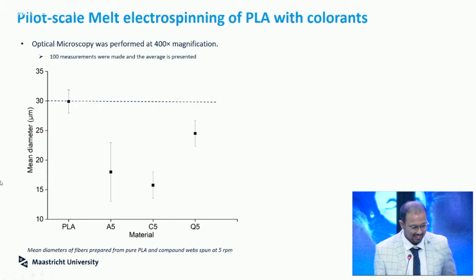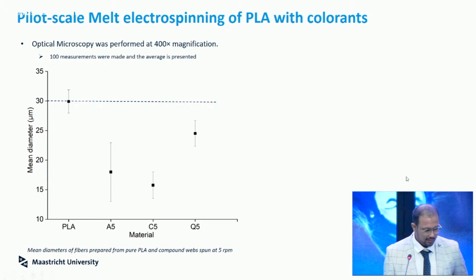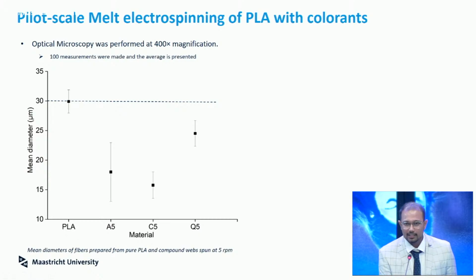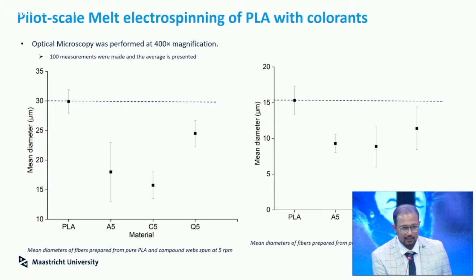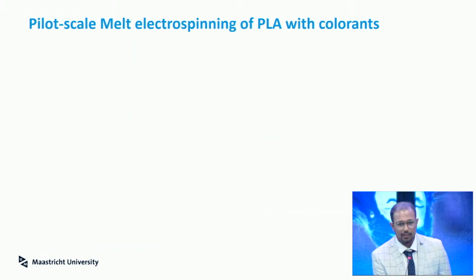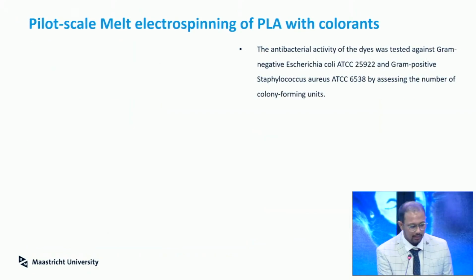Thank you, Prorector. So if you look at the graph in here, we did the trials, and then I measured the diameter of the filaments I made. As you can see in the picture here, for the same processing conditions, in terms of pure PLA, I got like 30 microns with higher throughput and 15 microns with lower throughput, which then dropped down to less than 10 micrometer when I was adding the colorants, which was also the intended outcome that we wanted to have, because we wanted to go lower with diameter so that it can have better filtration efficiency.